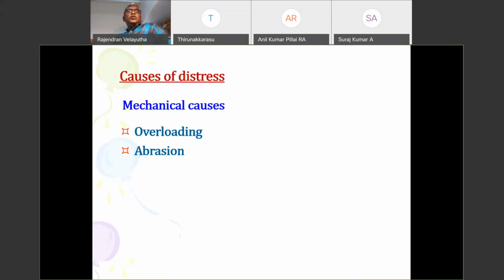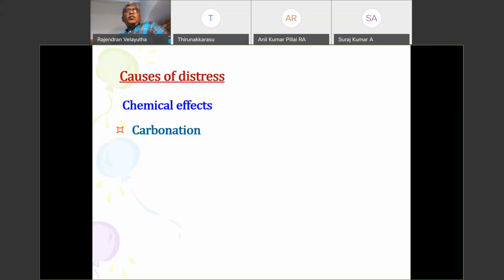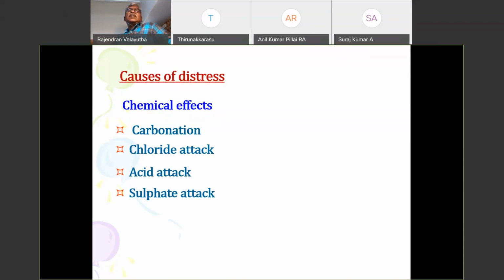Mechanical causes are of course overloading, abrasion, impact, wear and tear, and fatigue. Chemical effects are durability issues: carbonation, chloride, acid, and sulfate attack. These are all the issues taking place. Carbonation is becoming more predominant of late, along with chloride attack, because of a practice we have now. Once apartment cultures came into the picture, we don't paint the structures for about 10 years, and obviously carbon dioxide diffuses into the cover concrete and results in carbonation.